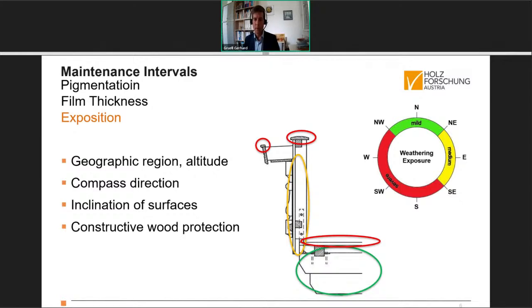So this is the influence of constructive wood protection in the end, which also goes down to detailing of all the wood constructions so that moisture traps and continuous high moisture content are avoided, because that is the reason for onset of decay by wood destroying fungi, which in the end lead to rot and the real loss of mechanical properties of the wood.